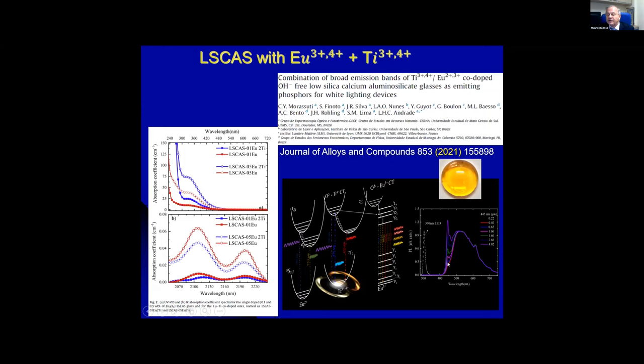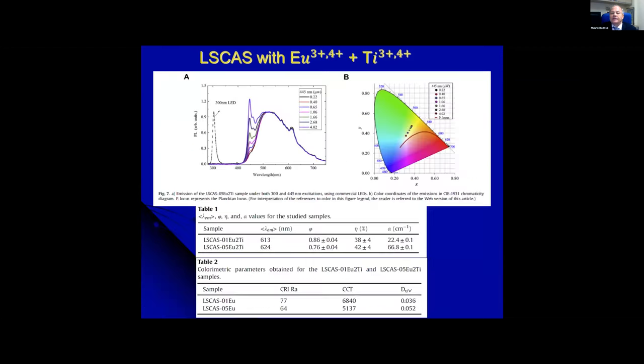This is a very important result because when you use crystal, you cannot block the blue emission as I showed in the beginning, because the YAG, for example, transmits a lot of the blue light. In glass, depending on the composition and the doping you use, you can control the emission in the blue, and then you get a safer spectrum for the eye and for vision in terms of the ideal white light. This is the data from this paper. I just selected this graph again to show you.